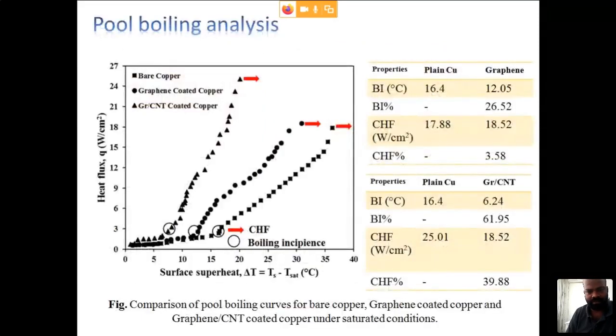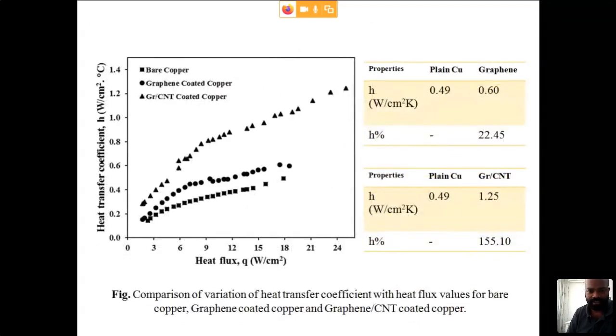Pool boiling analysis. This is the pool boiling heat transfer curve. So you can see that when we have used this graphene CNT heterogeneous combination as a pool boiling surface, the performance increased very high. You can see the CHF as well as heat transfer coefficient increased a lot as compared to plain surface as well as only graphene coated surface. This is the heat transfer coefficient. Again, the heat transfer coefficient also increased as compared to the other two surfaces.